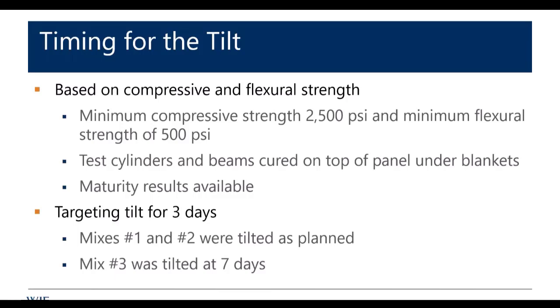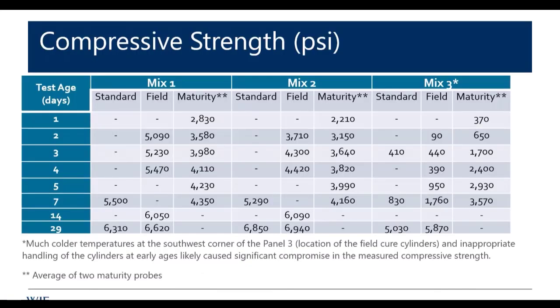We basically monitored maturity. We targeted for 3 days. Mixes 1 and 2 tilted as planned. Mix 3 laid there a little bit. And we were showing very little strength gain based on the cylinders. This is the results of the testing. We have estimates from maturity as well as what they were measured. And if you look at the ones for mix 3, it's showing like nothing, right? Very low strengths, but the maturity was predicting much higher.